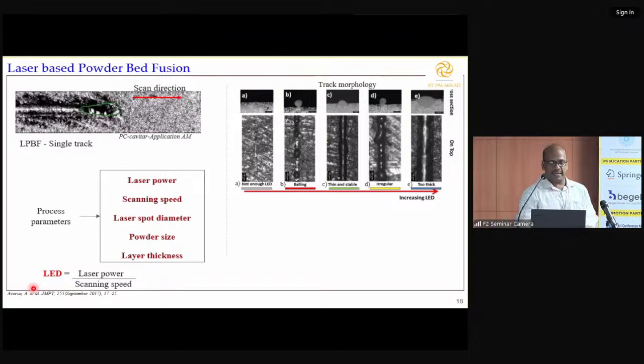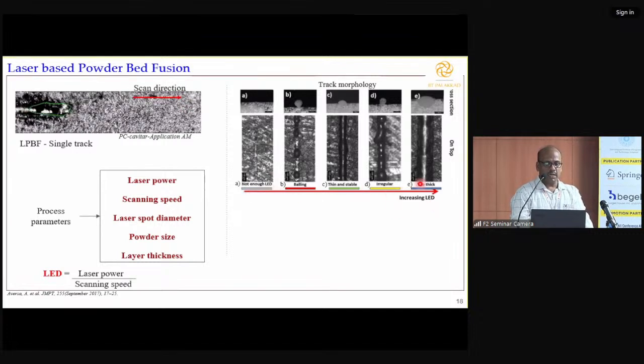When you see over here, the track morphology, laser energy density is increasing from A to E. If the laser energy density is very low, there is no track at all. Whereas if you go a little more, it gives defects like the balling defect. I'm supposed to have a continuous deposition. Instead, it is deposited but like balls. Then I get a thin and stable track. This is the required single track.